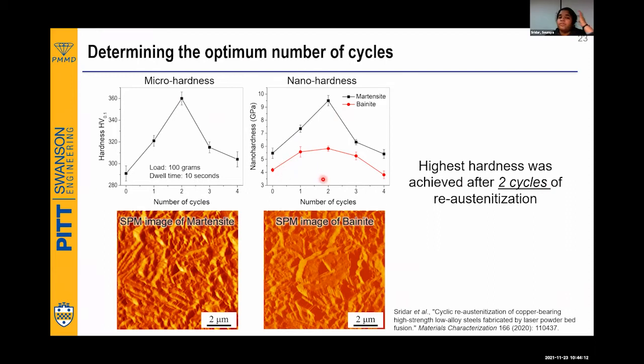In nano indentation, you can find a particular phase and make the indent in that phase. Here I'm showing 2 SPM images. SPM means scanning probe microscopy, which is generally attached to the nano indenter, such that you can scan through and see the topology of the microstructure. I already showed in the SEM micrograph that the martensite and the bainite don't have surface relief. So you can see that this is a nano indent in the martensite, and this is a nano indent in the bainite.